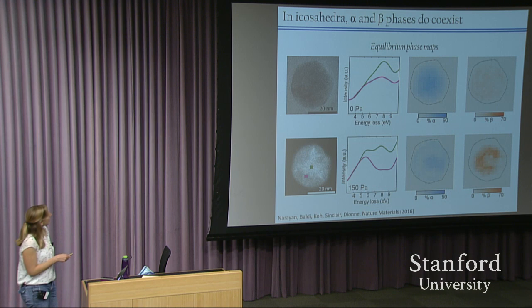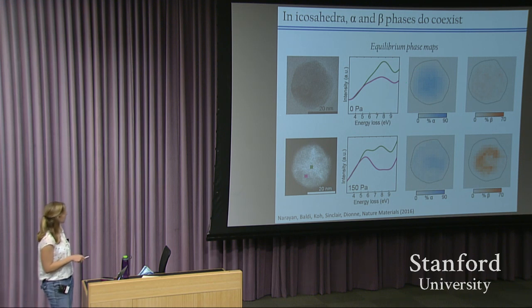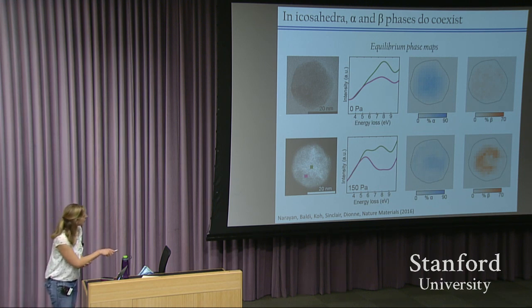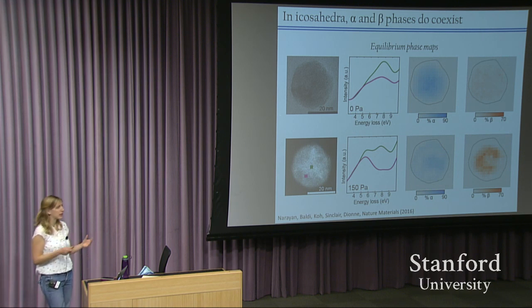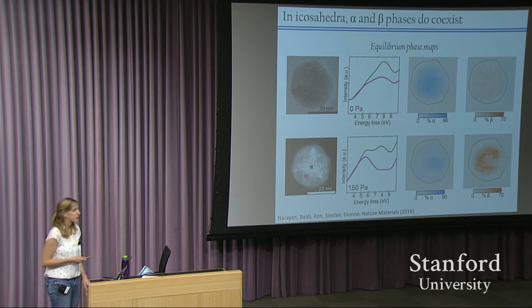But if we do that for icosahedra, at low hydrogen pressures or no hydrogen, we essentially just have the alpha phase in the core. But then when we move up to an intermediate hydrogen pressure, we have the alpha phase still existing in the core and the beta phase in the shell. So we have parts of the nanoparticle that aren't transforming to the beta phase. And it turns out that occurs even up to the highest hydrogen pressures that we can access.